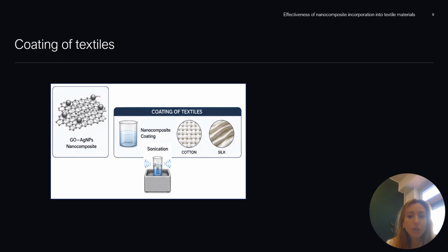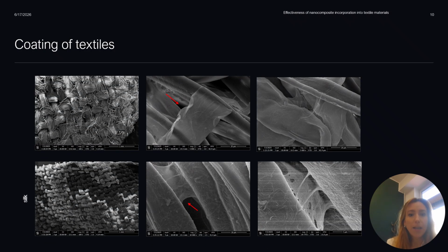Following sterilization, cotton and silk fabrics were sonicated in the nanocomposite suspension, enabling effective deposition of the nanocomposite coating onto the textile fabrics. Importantly, sonication did not adversely affect the structure of either textile material. After coating, the samples were dried and then analyzed to assess the uniformity of the nanocomposite coverage and to confirm the successful incorporation of graphene oxide, silver nanoparticle nanocomposites into the textile fabrics.